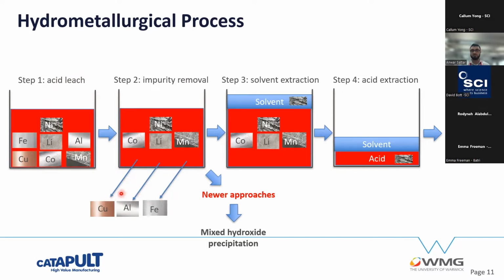You remove those. Then traditionally, the next step is you selectively extract one of these metals from the acid. So you add a solvent to it. The solvent selectively extracts the nickel, for example. And then you transfer that nickel from the solvent back into an acid, and then you precipitate it out. Now, of course, it's not that easy because every time you take the nickel out, you might take the cobalt out or the manganese out because they're very similar metals. So you have to do a number of different extraction steps before you can get the purity required.